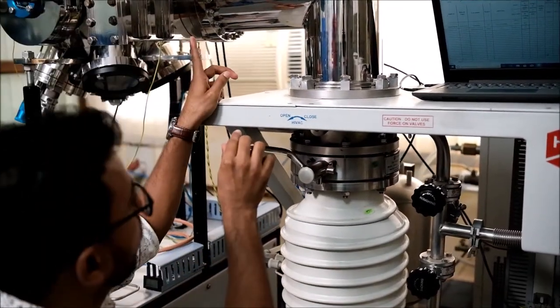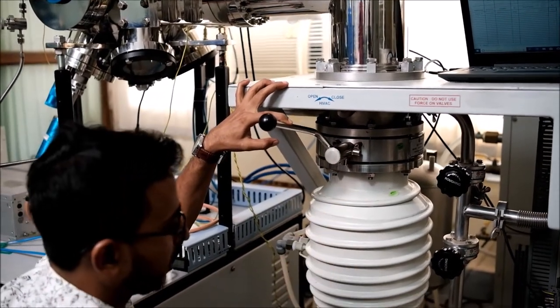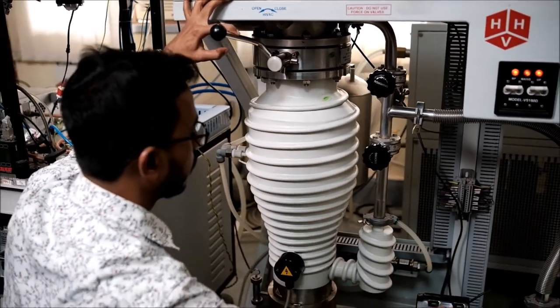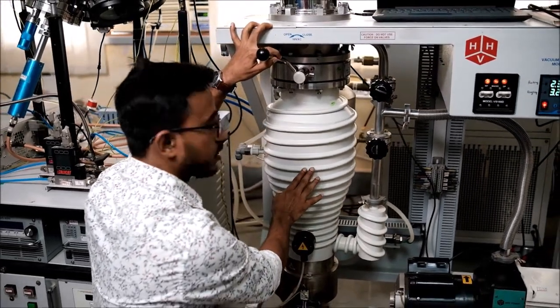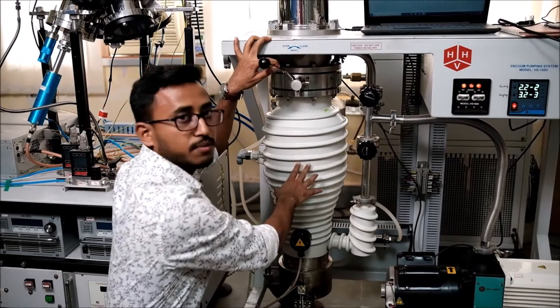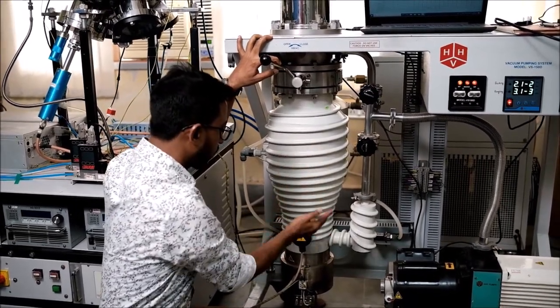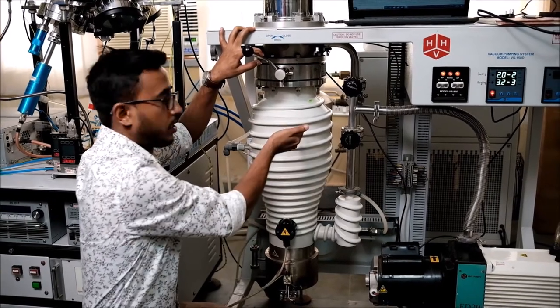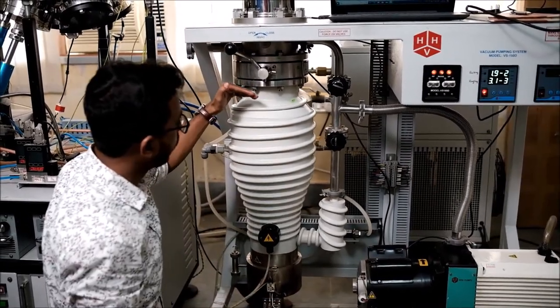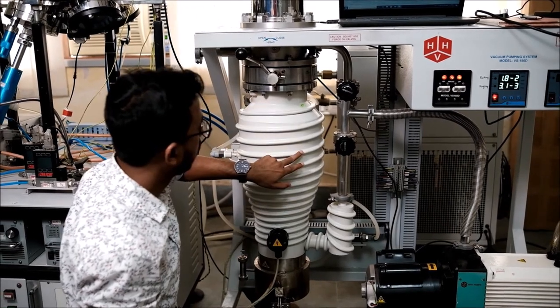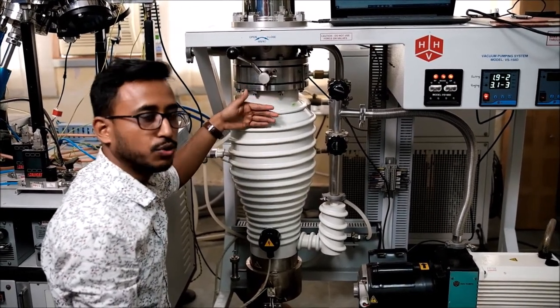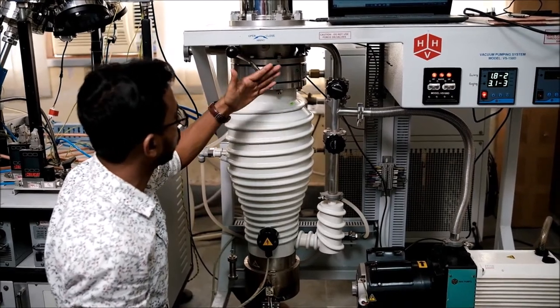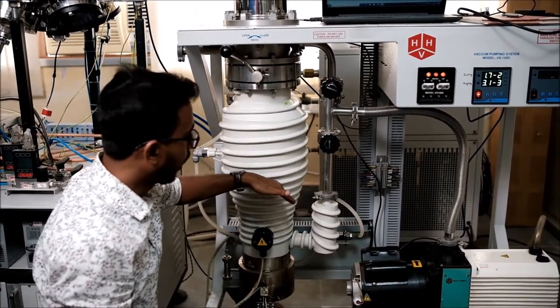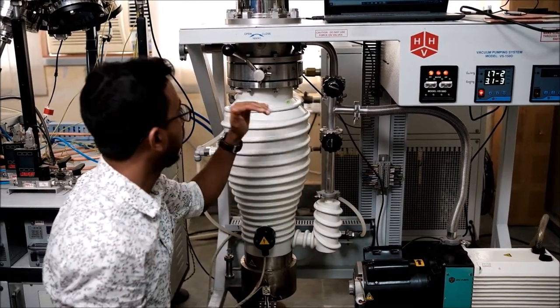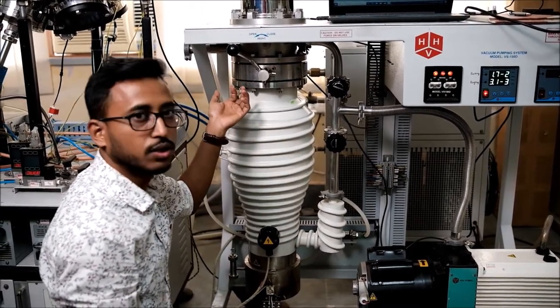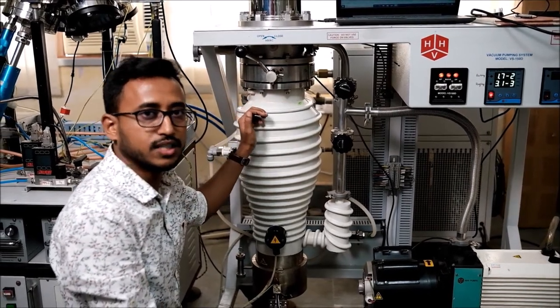So this way now the chamber is connected to the diffusion pump, and at the back of the diffusion pump this rotary pump is connected. Now inside the diffusion pump chamber, the mechanical structure is maintained in such a way that it converts this oil vapor into a jet, and when the jet enters from center to the wall, it transfers its momentum to the air molecule, and thus the air molecule from the top part comes down to the bottom part, and the rotary pump takes out the air molecule, and thus the pressure gets down, and it can do this till it reaches 10 to the power minus 6 millibar of pressure.